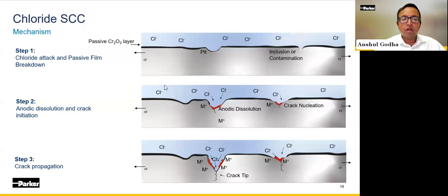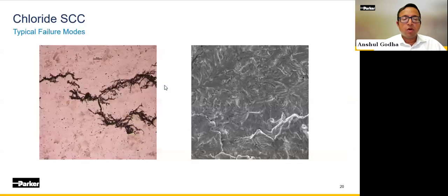And even after the cracking is initiated, this dissolution continues and the crack just propagates freely. This is what a typical chloride stress corrosion crack would look like, where you have the branching that I spoke of earlier, but also notice that the nature of the crack is transgranular, because the cracks are cutting across the grains. We have a view here both of the microstructure as well as of the fracture surface of such a crack.